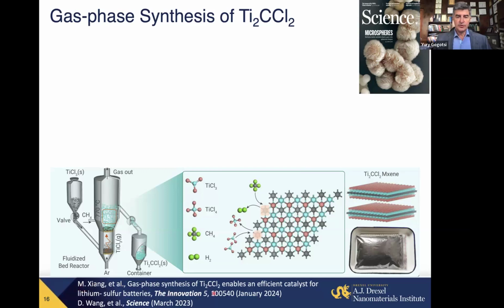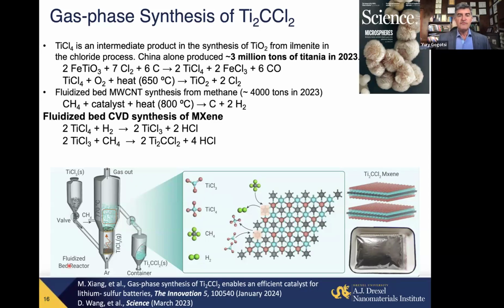another very important paper appeared on gas phase synthesis of titanium carbide MXene using a process which is actually very similar to synthesis of titanium dioxide or nanotubes, which are used now in all cell phone, computer batteries everywhere. 3 million tons of titanium dioxide were produced in 2023 just in China alone. So in this process, when people start with iron titanate, titanium chloride is formed as intermediate product and used by heating with oxygen at high temperature to make titanium dioxide. So it's a white paint on the walls everywhere. This is this titanium dioxide.